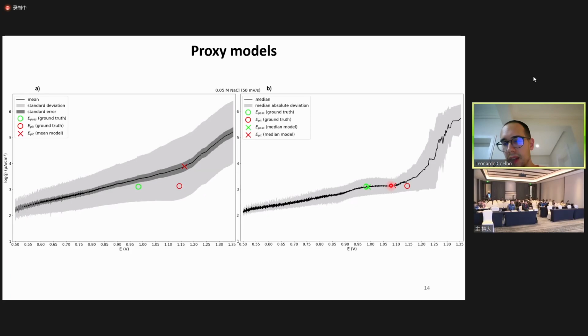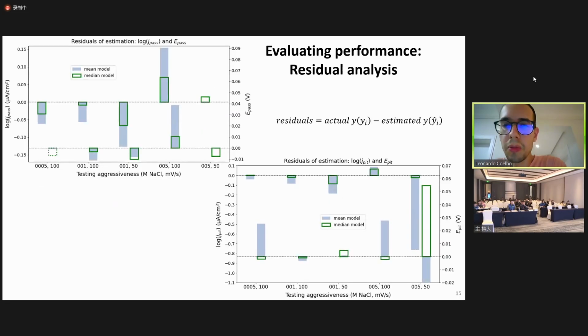However, if we input the median, results were not that bad. So the argument would be, instead of doing all of that labeling work, which can be quite extensive, if we could simply find the median of the distribution, the median could do a very good job and a much simpler job, with much more, I would say, industrial interest as well. So we performed residual analysis to really show that the median, which I show in green in those box plots, very often outperformed the mean proxy model, regardless of the descriptors we were trying to estimate.